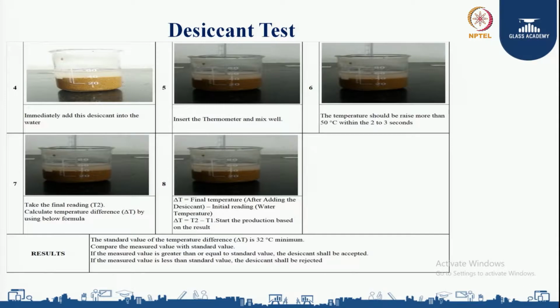The temperature should rise more than 50 degrees centigrade within 2 to 3 seconds. Take the final reading, that is T2. Calculate the temperature difference using the formula: delta T equals the final temperature after adding desiccants minus the initial water temperature, that is, delta T equals T2 minus T1.